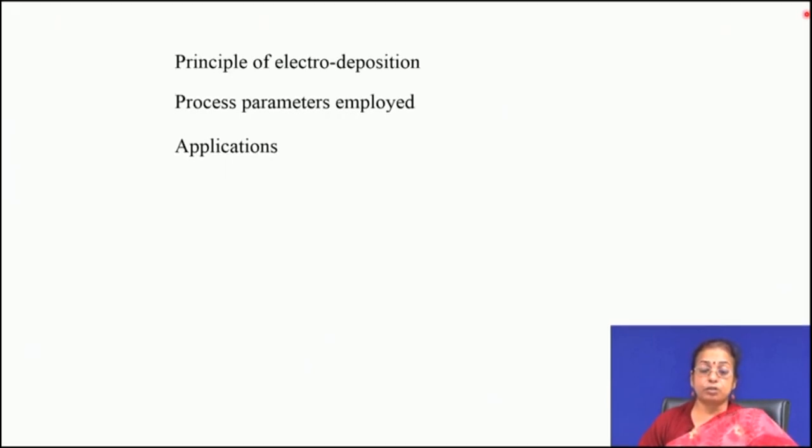The metal deposition which occurs may be for corrosion resistance or wear resistance applications, and usually this deposited layer has some kind of bonding with the substrate at the interface, with some diffusion as well. On the other hand, in chemical conversion coating, the substrate itself is converted to its compound, so the interface is very adherent in nature. In electro and electroless deposition, there is a very sharp interface.